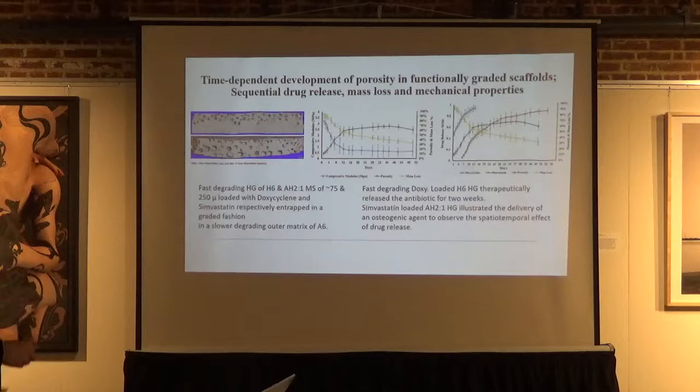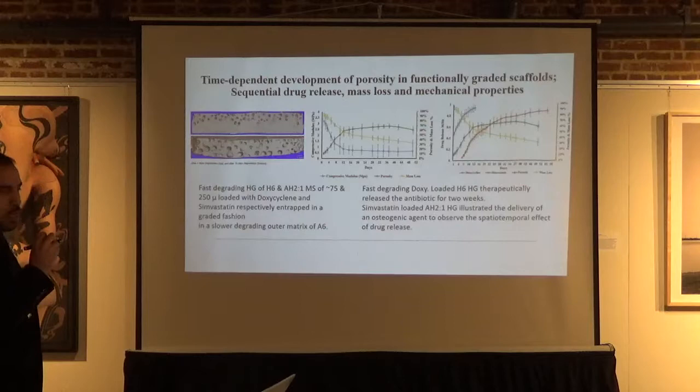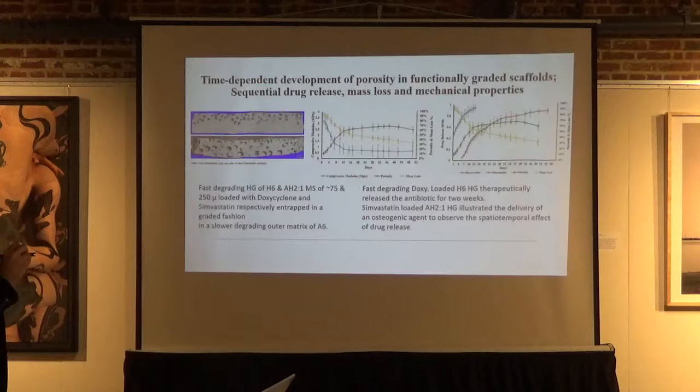In this case, the top layer consisted of hydrogel microspheres of H6, which was hydrophilic and was loaded with doxycycline, which is an antibiotic. As you can see, doxycycline was released therapeutically for 2 weeks, while the simvastatin drug was loaded in the AH2:1 hydrogel microspheres, as you see in the bottom, and it was released throughout the whole time. So not only were we able to hold the mechanical integrity of these scaffolds from the beginning, we were also able to have sequential drug release.